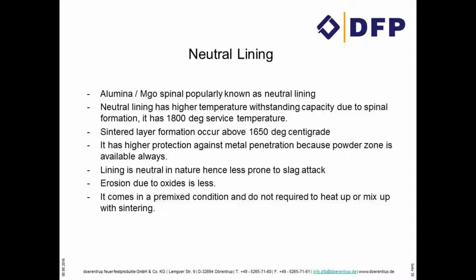The sinter layer formation, normally when we say for the refractory, there are three zones: sinter zone, semi-sinter zone and powder zone. In neutral lining you will find a very thin and very strong sinter zone, and the powder zone will still be there in the lining. So sinter has a protection. When any metal penetrates through the refractory, it will reach the powder zone and then it will be stopped. So it increases the protection of your furnace.